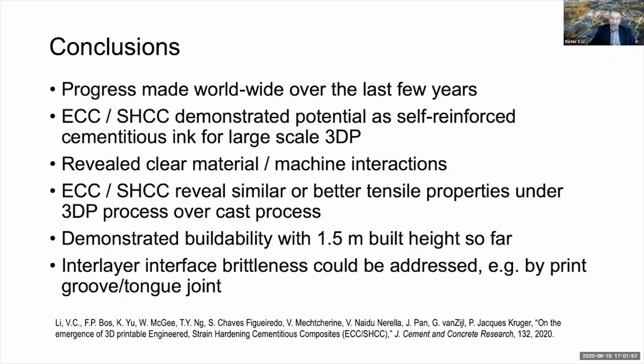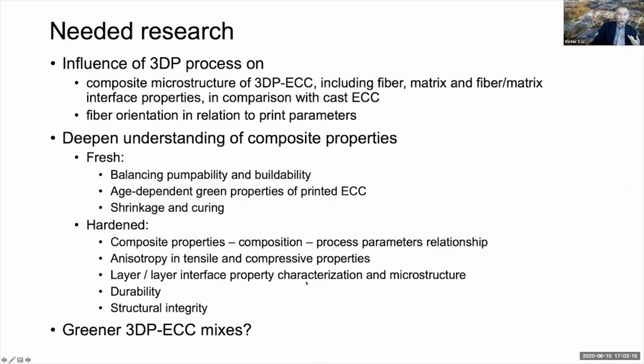So far, as I mentioned, we have accomplished building a 1.5 meter tall twisted column. This is obviously not enough, so there is a lot more work that needs to be done, and work where we need to maintain a good balance between pumpability and buildability. Further, there is a need to address the brittleness of the interface between two printed layers. We have demonstrated some initial success of using a groove/tongue joint, but I believe that there is much more that can be done. Let me go a little bit more into needed research in the future.